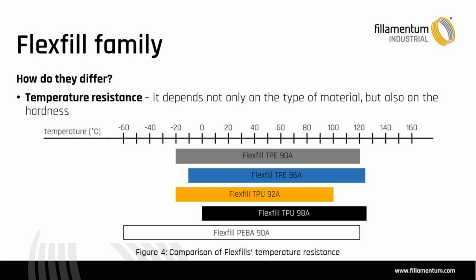The softer the material, the lower the temperatures it can resist at both ends of the range. Regarding the low temperature resistance, the best is PEBA. It's usually used for ski boots and some outdoor applications because it can resist down to -40 or even -60 degrees. So this is one of the best materials for this application.